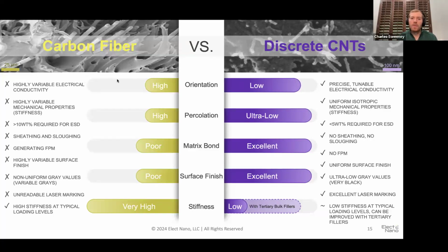And so with the next generation of 2 nanometer, 1 nanometer based devices, you're actually going to have to get a lot more intentional about making sure that everything that interacts with these devices on the manufacturing stage is tightly controlled for the electrostatic properties of the material, its surface resistance, volume resistance, to control static charge buildup. And so carbon fiber is not very good at that. And it turns out that carbon nanotubes are excellent at that. But the key is the dispersion component.